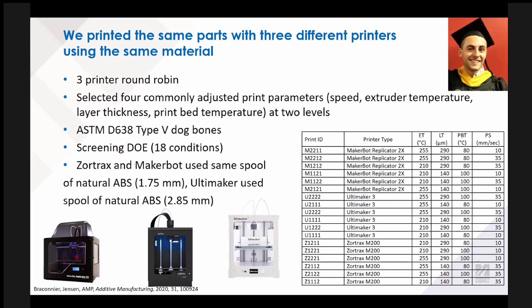This work was performed by Dan Ricanier, who did his master's in my group and is now doing his PhD at Northeastern. In this project, we did a 3-printer in-lab round robin. We used versions of these 3 printers and printed dog bones out of ABS. And we adjusted 4 commonly adjusted print parameters: print speed, print bed temperature, layer thickness, and extruder temperature. We had 2 levels of each of them.